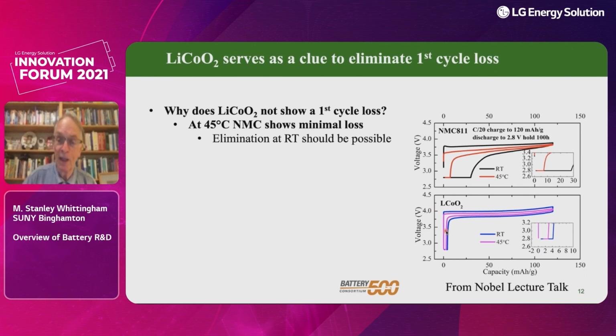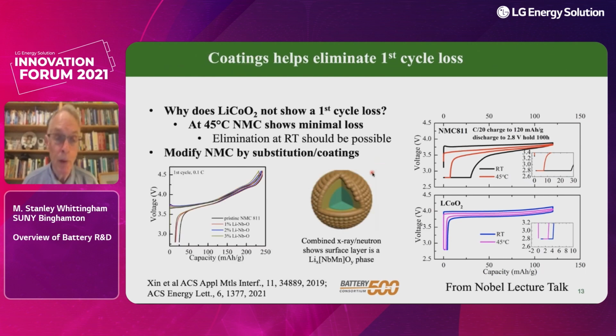You should point out lithium cobalt oxide and lithium-rich cobalt oxide are two separate phases. So at this point, we've got a two-phase reaction. But we assumed if this lithium cobalt oxide can work, then we should be able to modify the structure of the 811 to make it behave like lithium cobalt oxide. So we did this by modifying the NMC by both substitution and coatings. And for the material I'm reporting here, we actually used a niobium solution, lithium niobium oxide. So we started with pure NMC 811, then soaked it in a 1% lithium niobium oxide solution, or 2% or 3%. You can see it makes no difference. 1% is as good as 2 or 3%. When we do this, we're now eliminating about 40% of that first cycle loss.